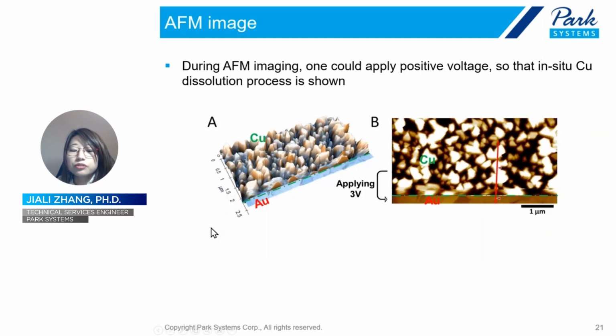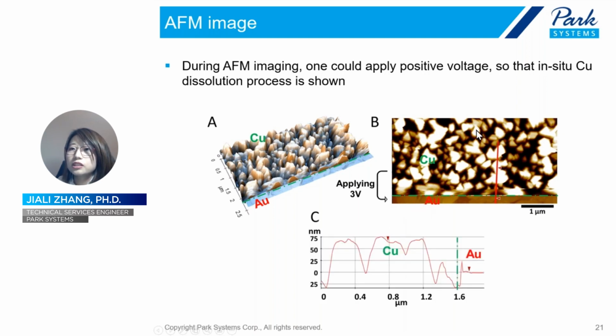The in situ dissolution of copper is also monitored with AFM, an example showing here. While scanning from top to down, in the middle of the image, we apply positive 3 volts, right at this horizontal green dashed line, and you will see that the high domain of copper island decreases in here and completely dissolves, and the bare gold surface is regenerated again. This is shown in our AFM image. You can see the trend as shown in our cursors that the 75 copper domain decreased and dissolved completely.